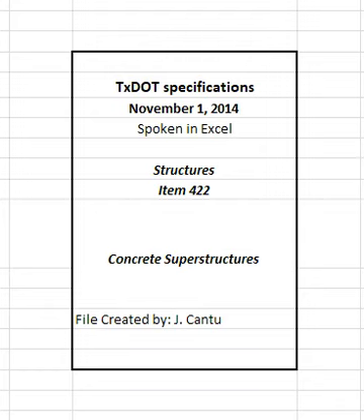Shade or wrap with wet burlap pipes through which concrete is pumped as necessary to prevent loss of slump and workability. Arrange and use chutes, troughs, conveyors, or pipes so the concrete ingredients will not be separated. Terminate such equipment in vertical downspouts, when necessary, to prevent segregation. Extend open troughs and chutes, if necessary, down inside the forms or through holes left in the forms.